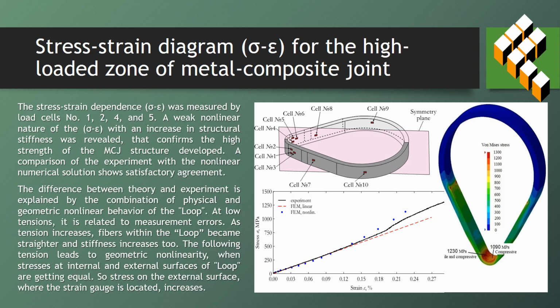The differences between theory and experiment is explained by the combination of physical and geometrical nonlinear behavior of the loop. At low tensions, it is related to measurement errors. As tension increases, fibers within the loop become straighter, and stiffness increases too. The following tension leads to geometrical nonlinearity, then stresses at external and internal surfaces of loop are getting equal. So stress on the external surface, where the strain gauges are located, increases.